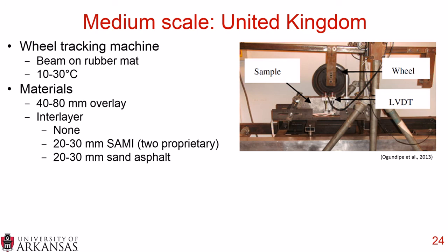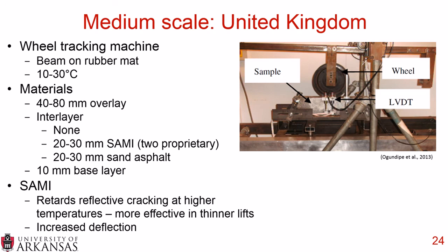And when they had those 20 to 30 millimeter thicknesses of the interlayer, they then had a thinner overlay. And then they had a 10 millimeter base layer. And this is what had the existing flaw in it in order to try and quantify the reflective cracking. And they found that the 2 SAMI mixtures retarded reflective cracking at the higher temperatures. In fact, they found that it was optimized at 20 degrees Celsius. It did retard at 30 degrees Celsius, but they didn't see any benefits at 10 degrees Celsius.